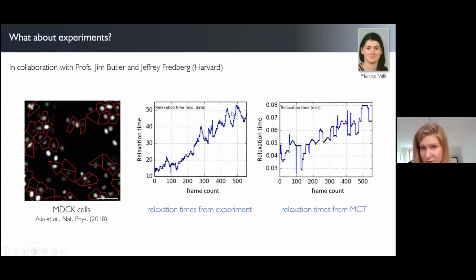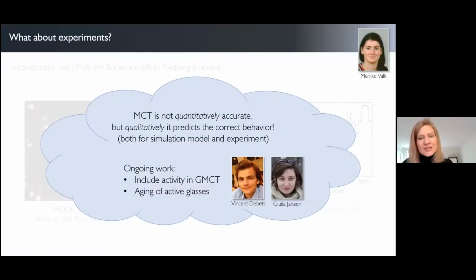These are the results from the experimental data, where the relaxation time grows as the cell layer matures. So it slows down monotonically in this case. And the mode coupling prediction also predicts the same monotonic increase in the relaxation time. Again, the quantitative numbers are off, but that's also something we would expect from mode coupling theory, that it's never really quantitatively accurate anyway. But qualitatively, it does a pretty good job also in these experimental data. So that's, I think,